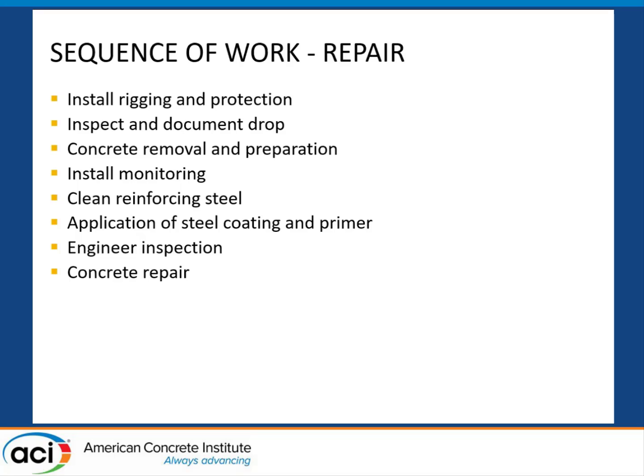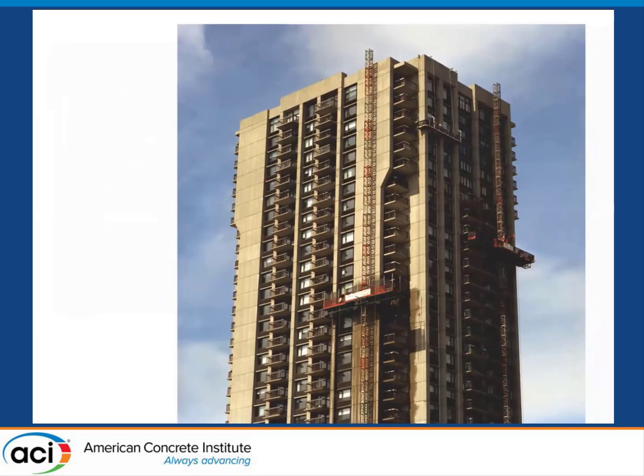And they followed a very disciplined sequence of steps, which I thought was a great approach. So here's just a photo of some of the work in progress. You can see the mast climbers here in the foreground and the background, and some swing stage, again, to get access to the structure. In this case, they're actually applying the inhibitor, and you can see that by some of these areas where the concrete is dampened with the initial application of the inhibitor, and then as it penetrates, it does dry out over time.